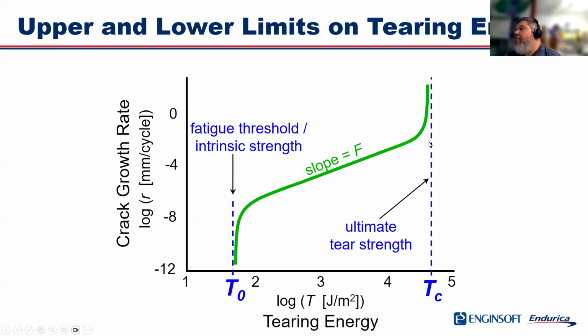So that would be a strength problem. As you back off on the energy, you're going to find that the crack growth rate slows down. And it's going to do that according to a power law that has a power law slope of F. You can see this if we're plotting on log scales, that's going to make a straight line relationship in the mid-range. And then if I back off sufficiently, the parameter T naught, this is my fatigue threshold. Sometimes we also call this the intrinsic strength of the rubber, and you'll see why in a minute.